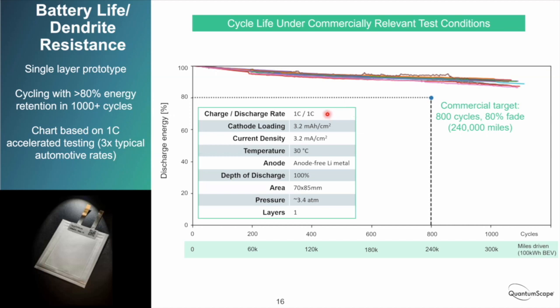This is at a 1C, 1C rate. So 1 hour charge, 1 hour discharge. That's pretty aggressive for a cycle life test like this that's typically done at C/3, meaning a 3 hour charge. So this is three times higher current density on every charge. The cathode loading of north of 3 milliamp hours per square centimeter is getting thick enough to have real energy in the cell. The temperature of 30 degrees is near room temperature. We're using the anode-free lithium metal anode configuration that I've described, going full depth of discharge over the full commercially relevant areas. Pressure is something I'll talk more about in a minute, but these tests are done under relatively modest pressure on single layer cells. So I think this was a pretty exciting proof that the materials and the processes that we use to make these materials are really capable of withstanding real world conditions, or even more aggressive than real world conditions here.